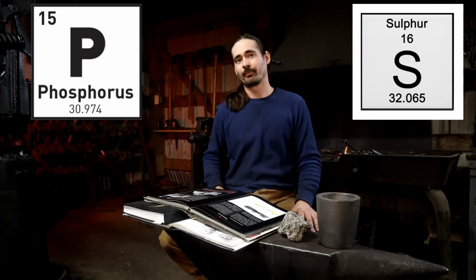For our practical purposes, from the standpoint of looking at bloomery steel, those two sword designs don't actually differ that much because they both utilize a version of the same material. One can argue, and from looking at the ores available in Europe versus Japan and the subtle differences in the smelting process, that the Japanese steel tends to be better as it contains less of the two worst possible contaminants in the steel, that is phosphorus and sulfur.